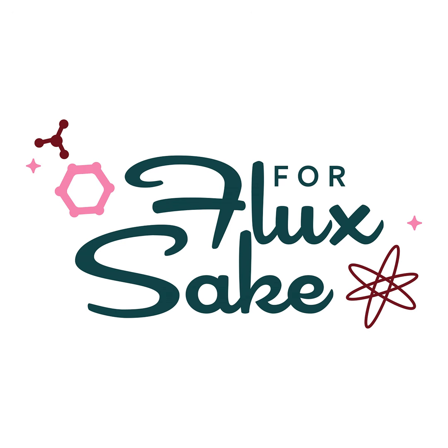But there is not an absolute dictum that you must fire to cone 10 if you can hit that 0.5% absorption. Now, Teresa brings up a good point that the actual results she's seeing in the real world don't match what the clay company is saying. And that I am not shocked by.